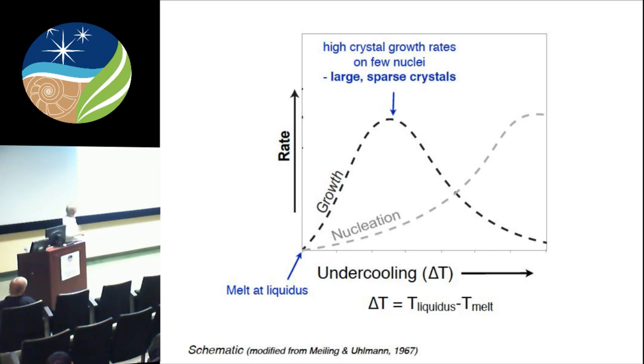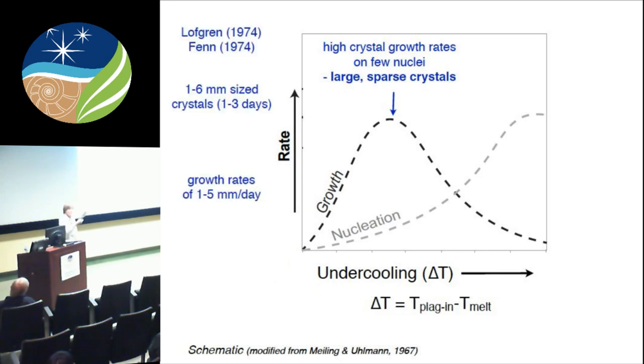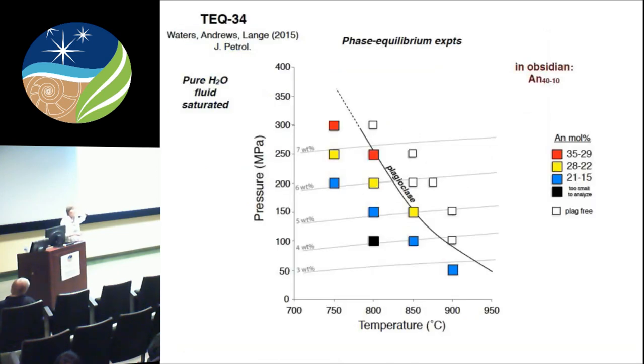Okay. And Fenn did the same thing with the alkali feldspar. So they found 1 to 6 millimeter size crystals in their experimental charges and growth rates of 1 to 5 millimeters per day. So this is experimentally shown, but the trick is you have to start above the liquidus and get an undercooling.